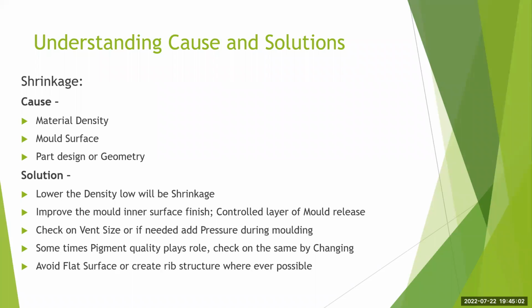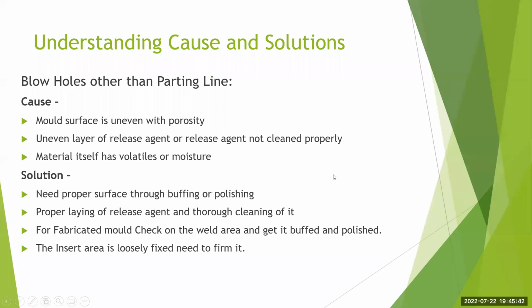That is the first caution your operator, or the person who is doing the mold cleaning or applying mold release, needs to know about. You have to be very cautious, and this will give you better product quality and inner surface also. Check the vent size. You can use pressure during the molding. Here also the pigment will play a vital role, and the product design needs to be looked at. Too much flat region or flat area in roto molding is going to give you a shrinkage issue. So you have to create ribs or other design structures, or give a bend or an angle, to reduce the shrinkage. That's a very, very important aspect.